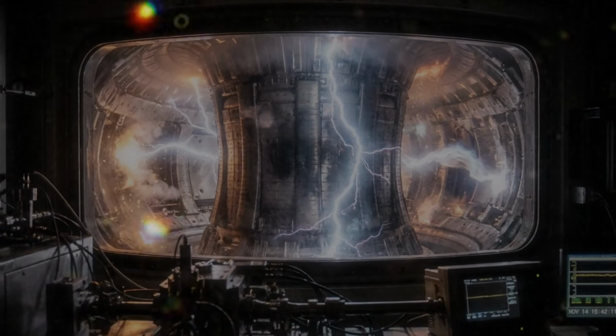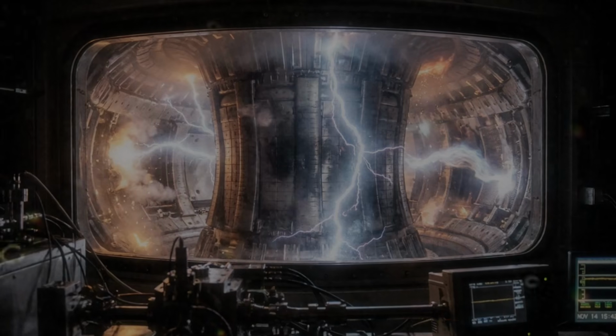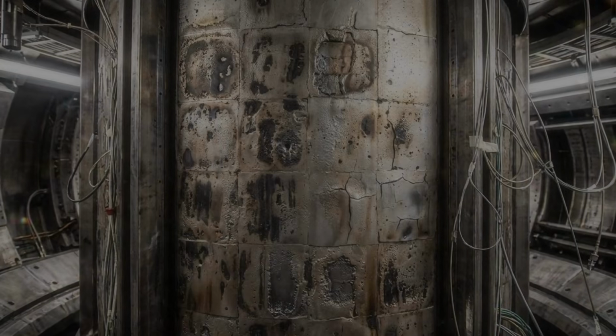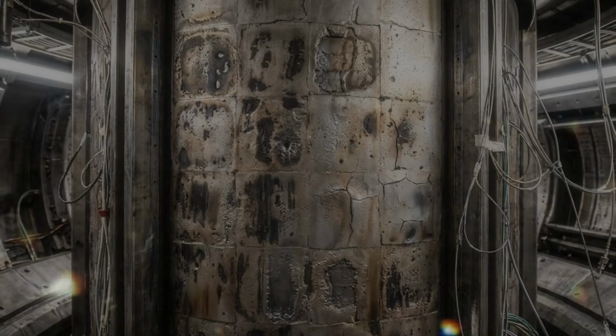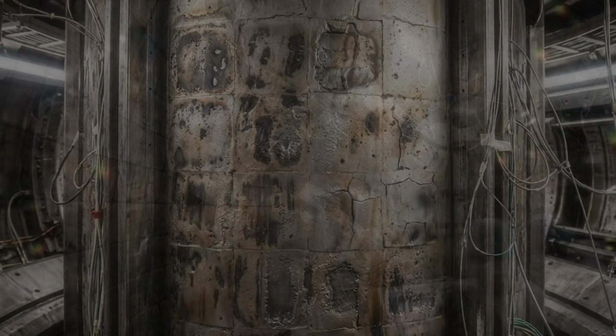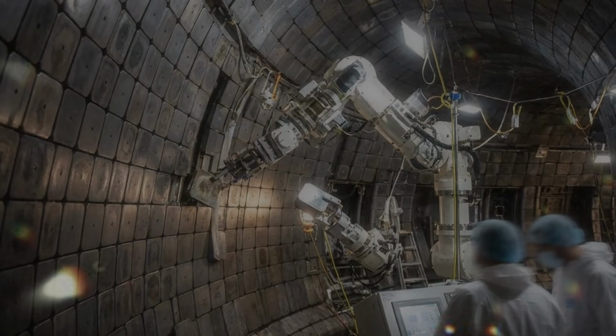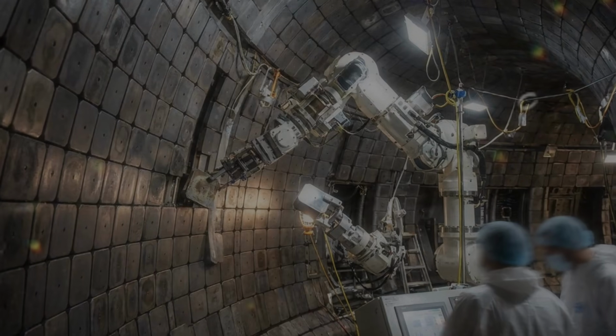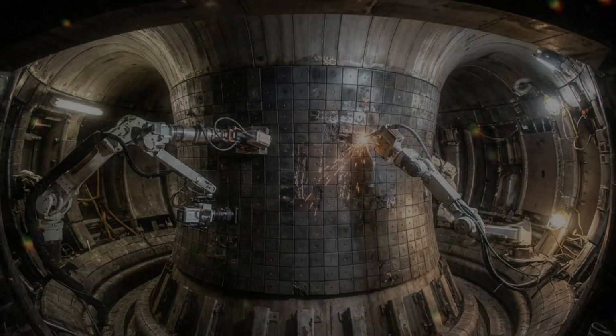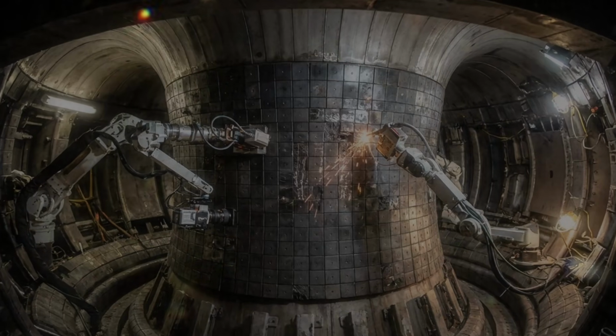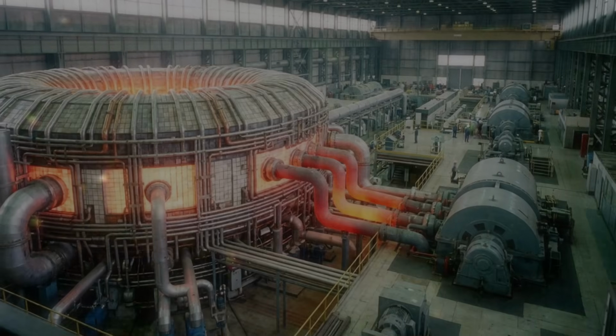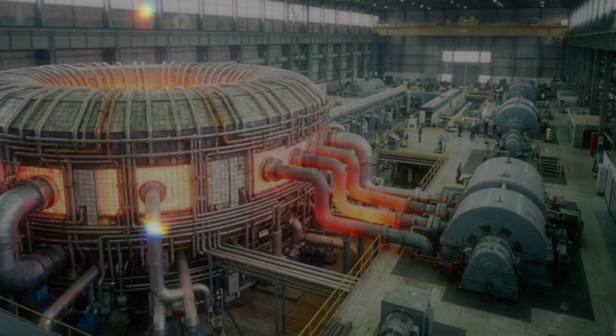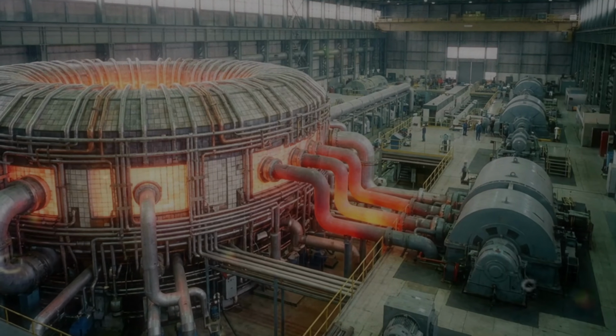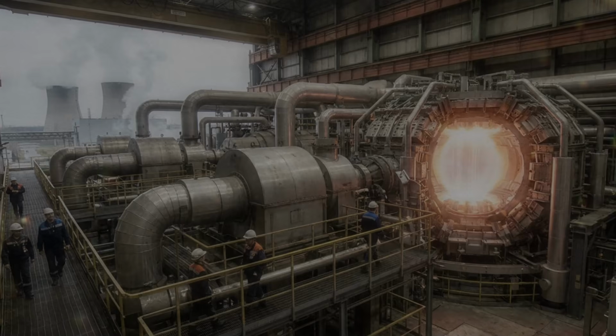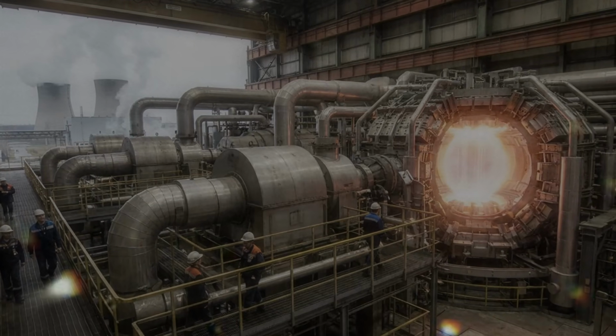This is not just a question of when the wall melts. Melting would be obvious. Lifetime is about when the material no longer satisfies all the requirements at once. Perhaps it has eroded too much. Perhaps it has cracked. Perhaps it retains too much tritium. Perhaps it has become too brittle. Perhaps it conducts heat poorly. Perhaps it releases too many impurities into the plasma. Perhaps it has become difficult to maintain safely. Failure is not always a single event. Sometimes failure means the material is still there, but no longer trustworthy.